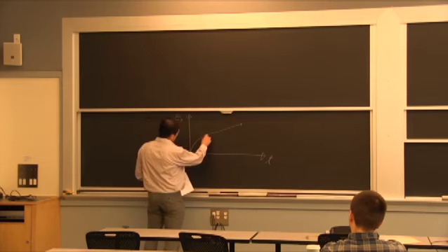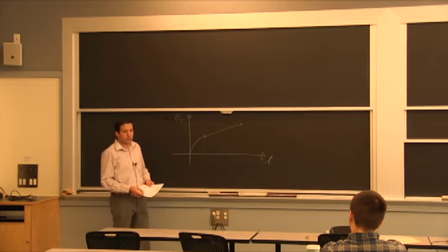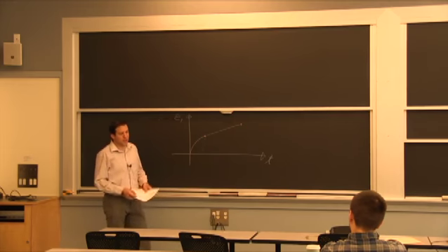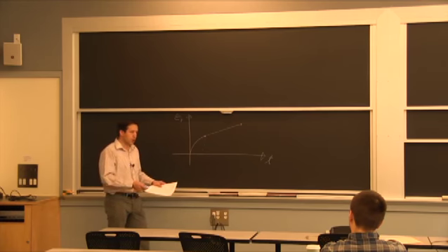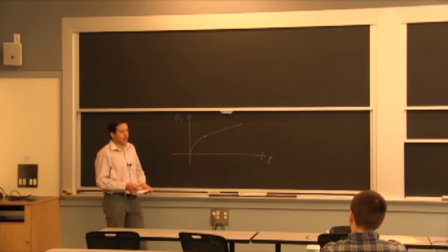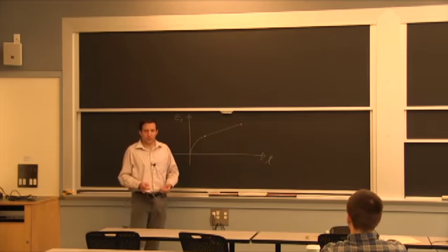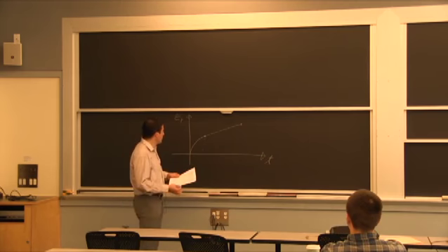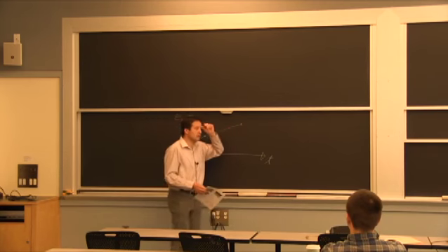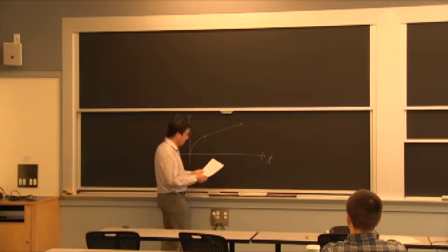For polymers, this portion here, we talk about viscoelasticity and stuff. With metals, it's a little bit the same story. Again, it's just small reorganizations that eventually lead you to an increment of strain, but you can't have a constant source of this deformation mechanism. When you come in this regime here, it means you have a constant supply of deformation sites, if you will, and we're going to go through what these are.